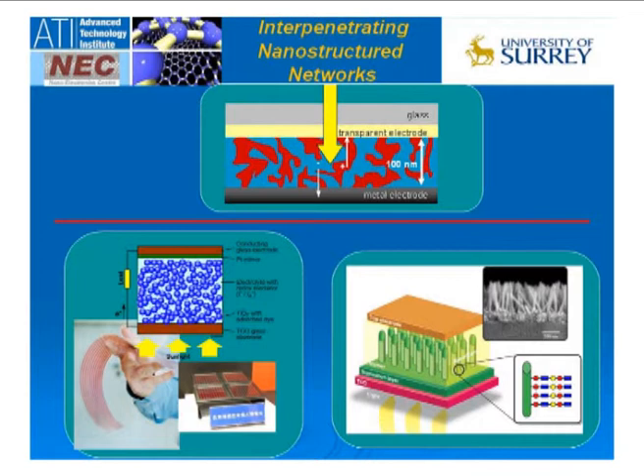Now, when you start looking at these materials and then looking at how it can be applied to structures, the other issue that you need to start thinking about that is extremely crucial is how does your photon get absorbed and what happens to the carriers that are created. The problem is quite simple, that if you have a material such as an organic, you need to have something between 100 and 200 nanometers of material in order to absorb enough carriers. Right? Now, think of the numbers we're talking about. Here we are talking about 100 to 200 nanometers. In crystalline silicon terms, we were talking about 100 to 200 microns.